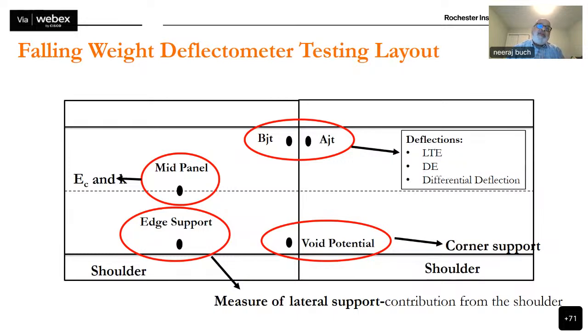There are different things you can do with the falling weight deflectometer. You can apply the weight in the middle of the slab to determine and back calculate the elastic modulus of the concrete and the modulus of subgrade reaction of the subgrade. You can test the joint for load transfer efficiency. Remember, these joints have dowel bars in them, to see how much deflection gets transferred from one side of the slab to the other, because you want to maximize that load transfer efficiency.